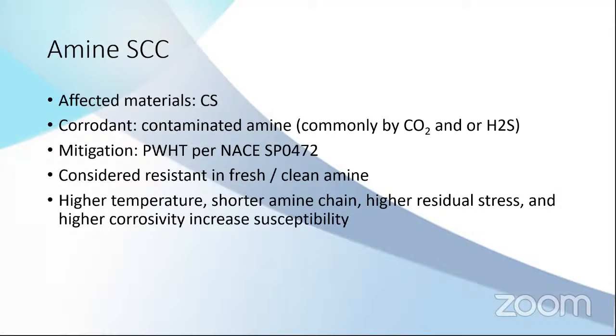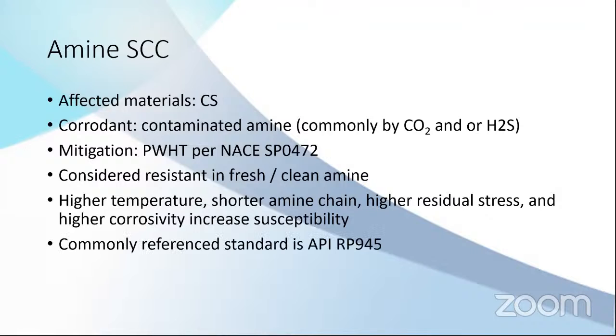And actually, it depends on the type of amine, depends on temperature, depends on the stress level. But from the safe side, normally when you have carbon steel in the amine environment, you just post-weld heat treat it anyway for the safe side. Because normally this amine system is an important system in the refinery. So if it's getting shut down because of corrosion, then you have a lot of problems in the whole refinery. So it's better to post-weld heat treat the welds when you have the amine service.